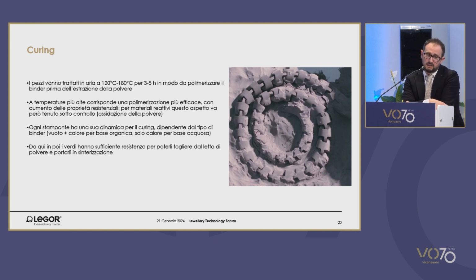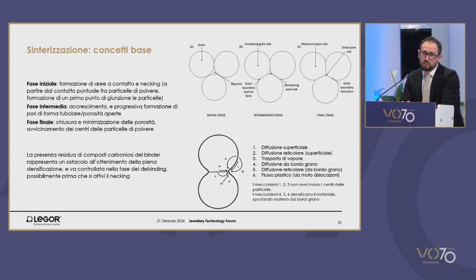The curing phase, which you saw before, during which the item is introduced in a chamber after being printed, envisages an intermediate temperature between 120 and 180 for 3 to 5 hours, depending on the quantity of powder that has to be cured. And it has to bear in mind that some materials might be reactive. This is the case of silver and bronze. Therefore, the curing process for these metals, which is carried out in air, could lead to tarnishing, to oxidation. And oxidation may be detrimental to the sintering phase.